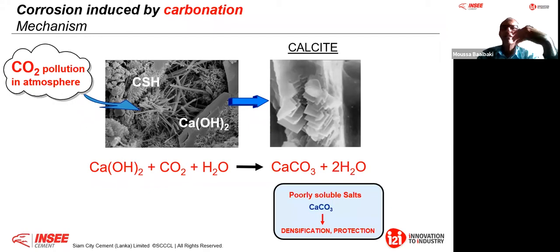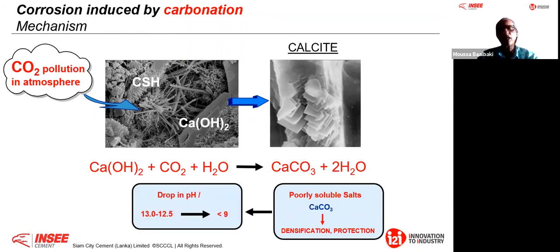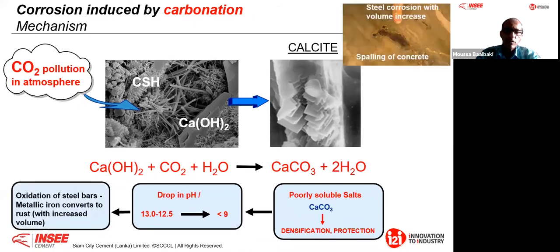But if this is continuously happening because you have high soluble CO2, high carbonation, and a certain porosity (it's not compressive strength, it's porosity), suddenly your pH can drop, because you have decalcification, with more and more of this Portlandite coming out. As soon as your pH drops and you are more acidic, your reinforcement gets depassivated. If your reinforcement is depassivated, it starts to grow, up to more than 10 times its volume. I'm talking about the steel bar.